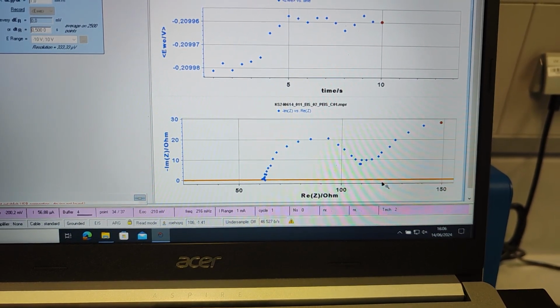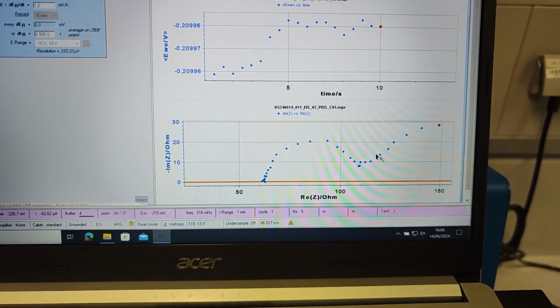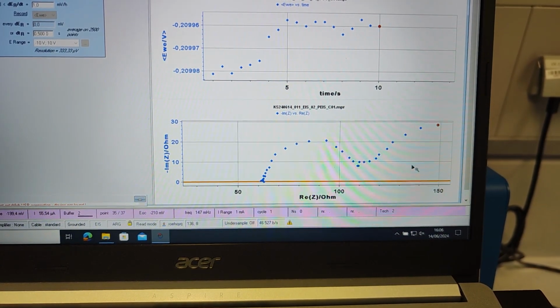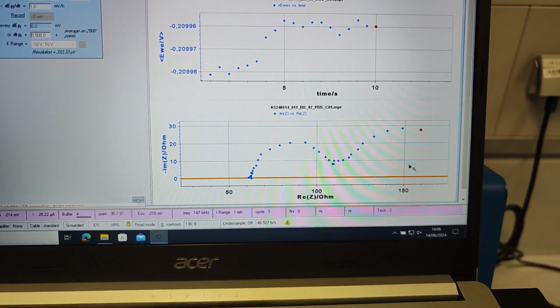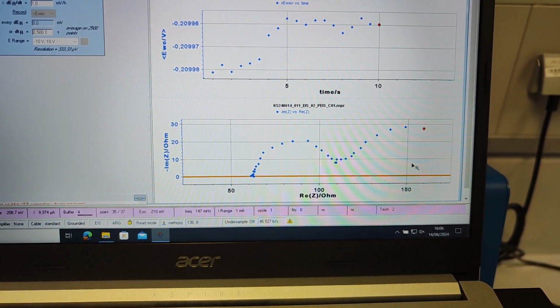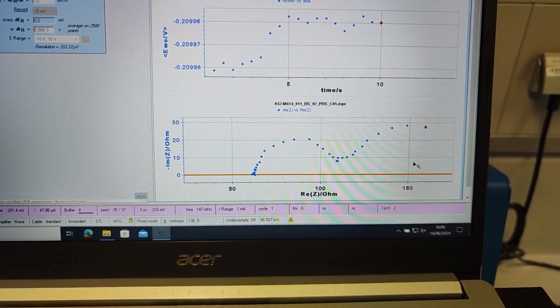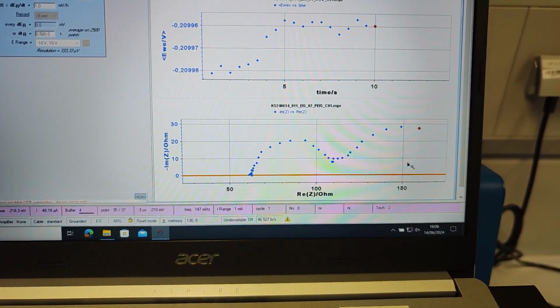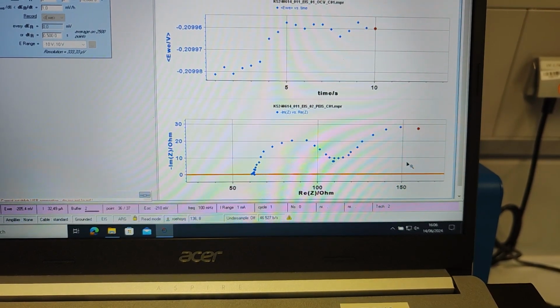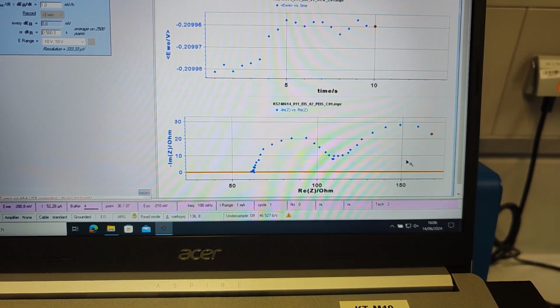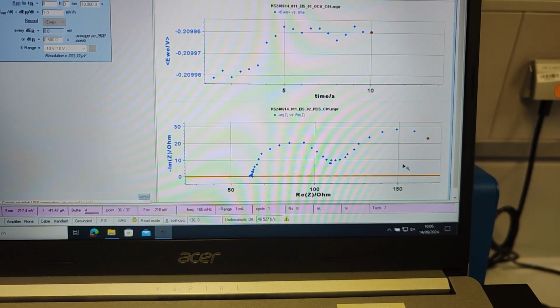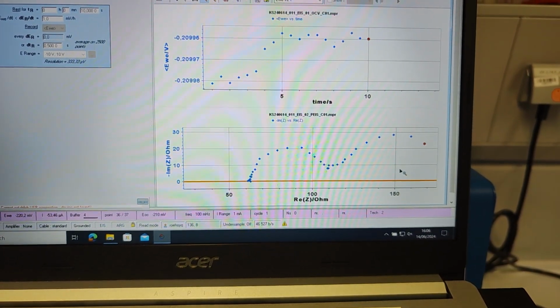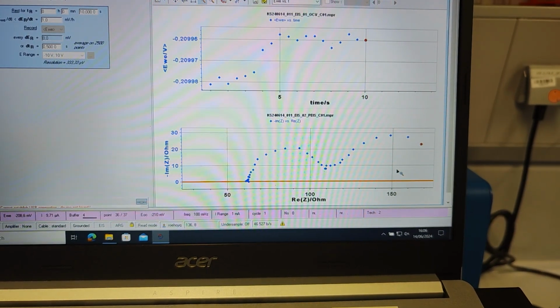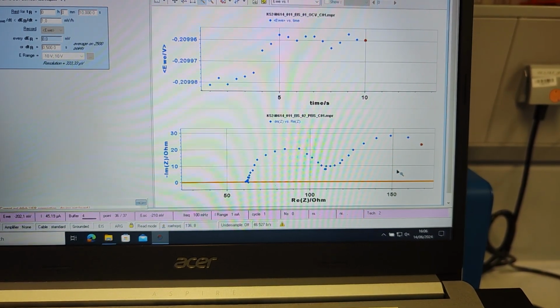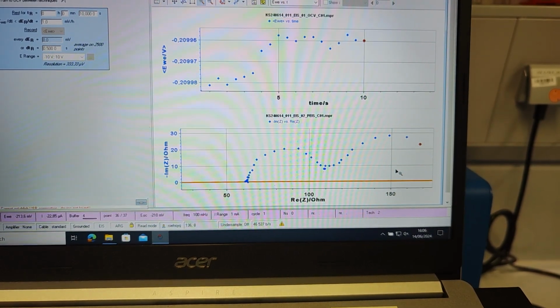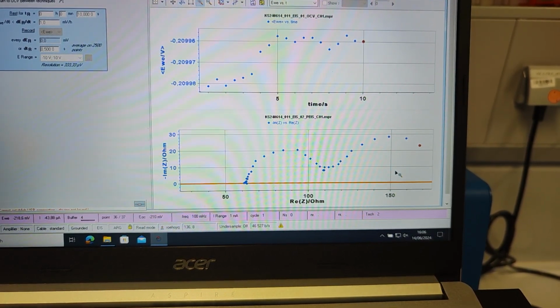Now going to the low frequency region, we can see that it doesn't keep a 45-degree line, it's leveling off. We already know this is a region where we get the diffusional behavior mostly. In this case, because we are rotating, we don't have this semi-infinite linear diffusion anymore, and therefore we cannot expect to get a 45-degree line. We get more like a second semicircle instead. At least it looks like this.